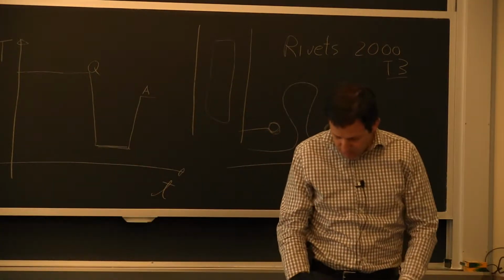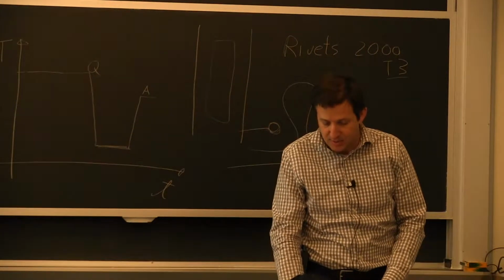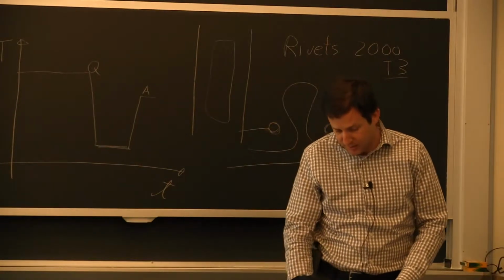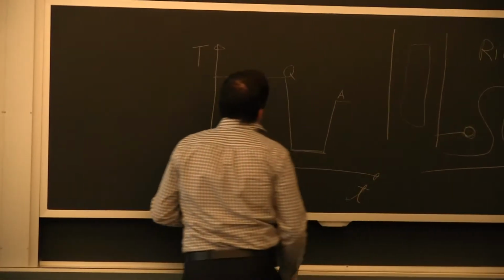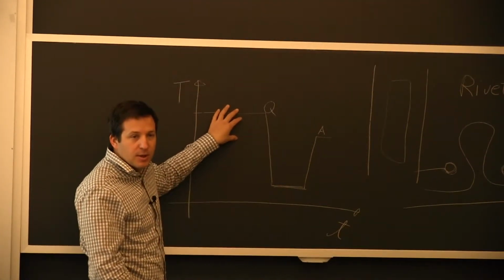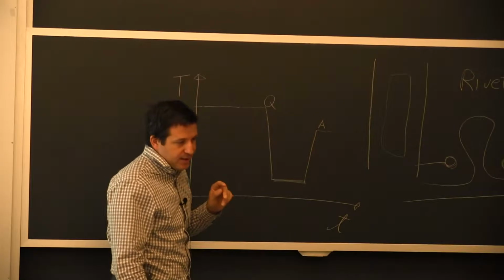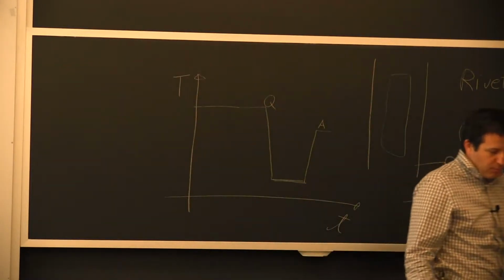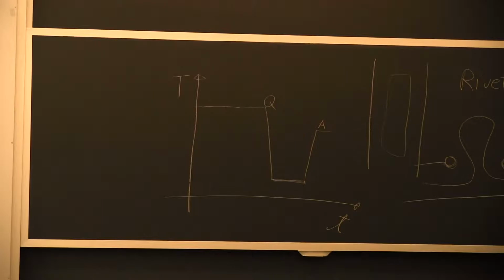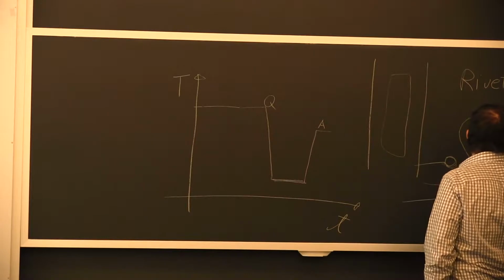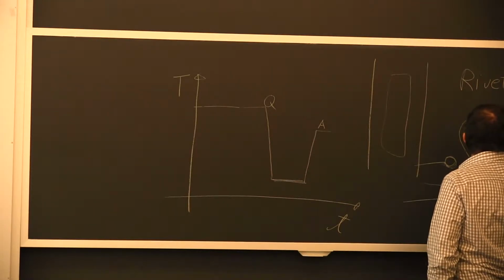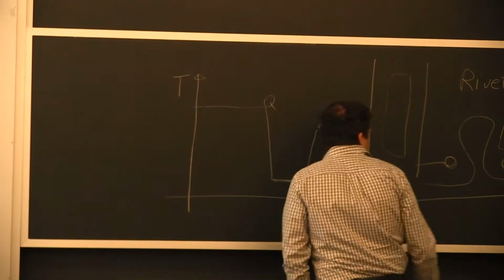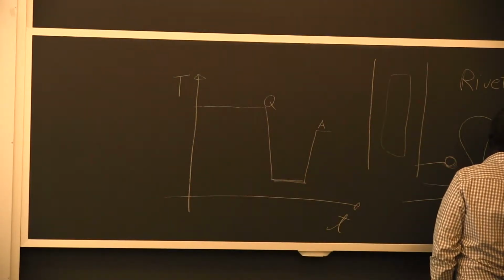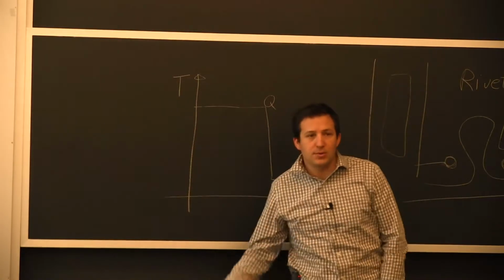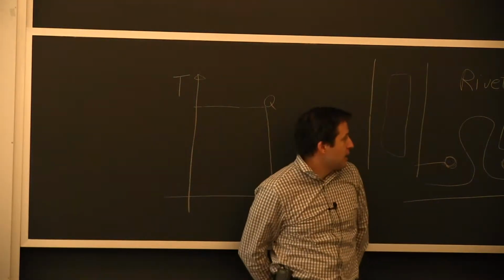The relevance of it with respect to this class this semester, as Professor Eager mentioned, is welding. In welding, you'll heat up the material in the heat affected zone, and that's essentially what will change this whole treatment. Professor Eager mentioned 6061 as being a very typical fabrication alloy. It's being welded a lot of the time in T6, which is the high strength temper. It's close to the peak hardness.